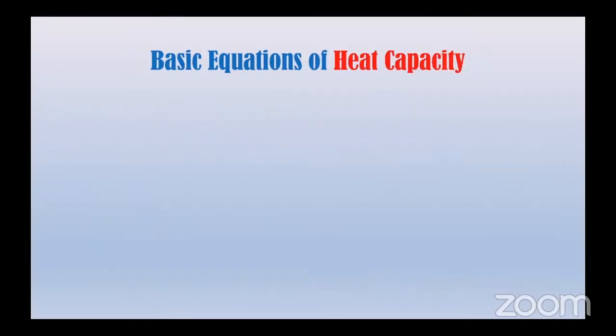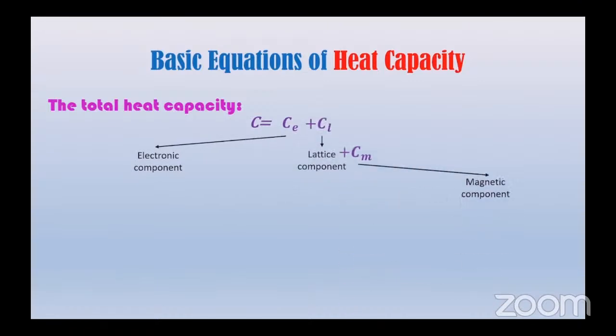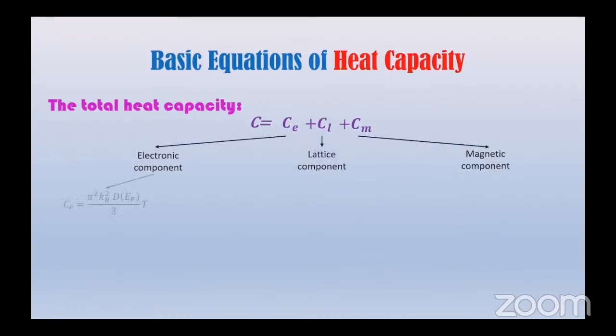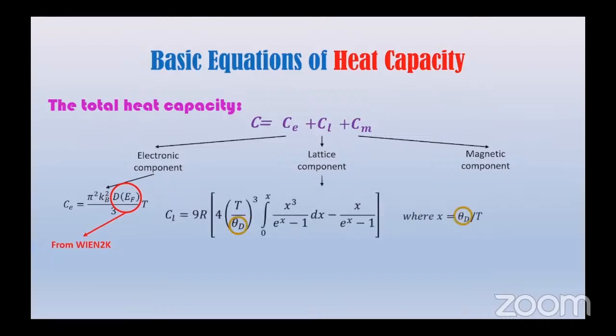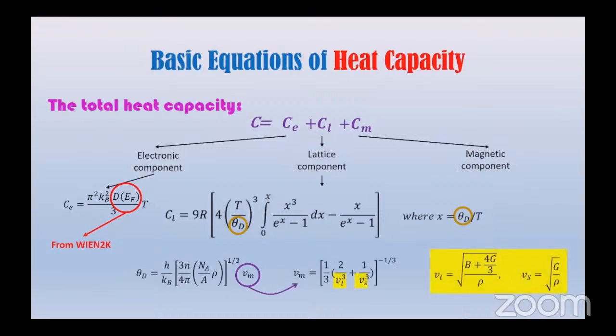Basic equation of heat capacity. The total heat capacity is a contribution from 3 components: electronic, lattice, and magnetic. The electronic heat capacity is calculated by simulating the electron density of states at the Fermi energy with the WIEN2k software. The lattice heat capacity is obtained by performing the integration where the Debye temperature is a limit. The Debye temperature comes from the longitudinal and transverse velocities, which are obtained from the simulated shear and bulk moduli. The magnetic heat capacity was calculated through mean field theory.